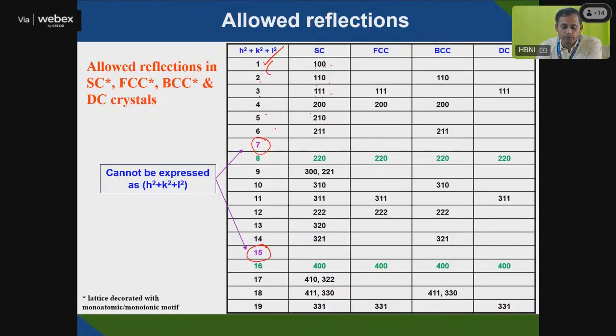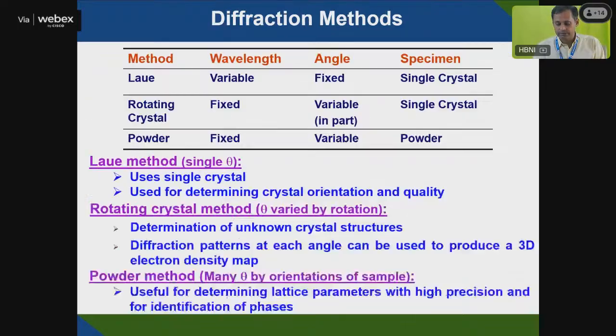So here 2 square equal to 4. So 2 square plus 1, 5. But 7, you can't express it as h square plus k square plus l square. Here 15 is not possible. That's why you can't express this. Therefore, no plane is possible in this case.